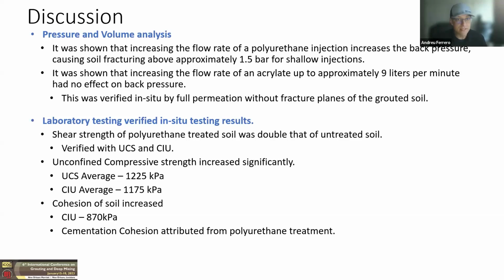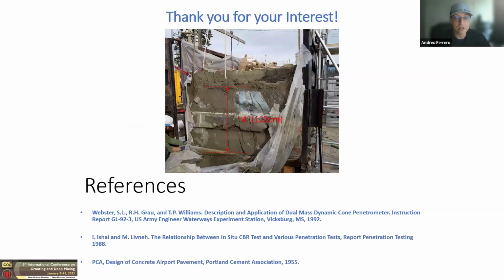We did a lot of laboratory testing, which was verified with our in-situ testing results. The shear strength of the polyurethane treated soil was pretty spot on between the in-situ testing and the laboratory testing, as was the unconfined compressive strength and the cohesion of the soil increase. And here is an image of that 4-foot high, a little more than 4-foot high cut open with the material treated there. And you can see me down there in the bottom left trying to measure some stuff.